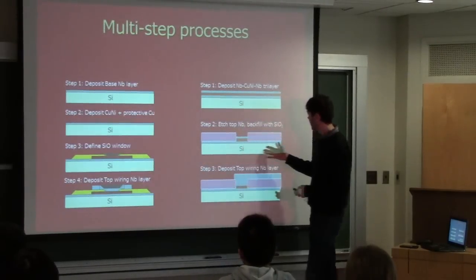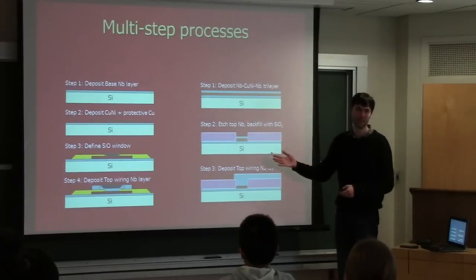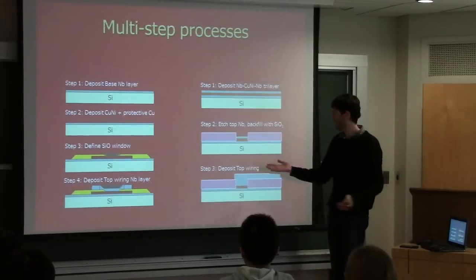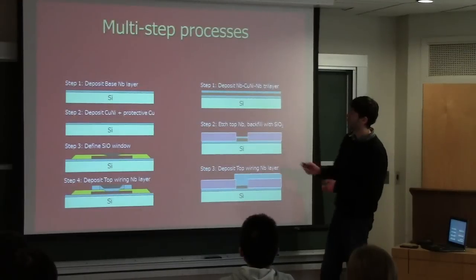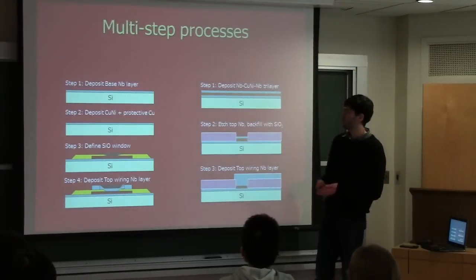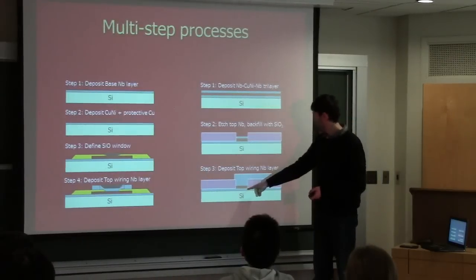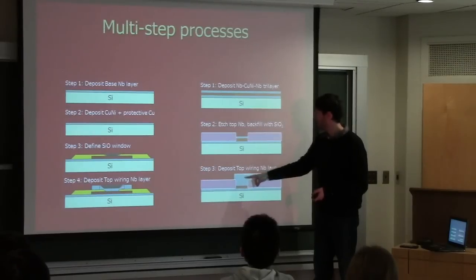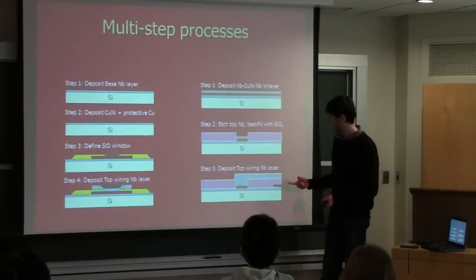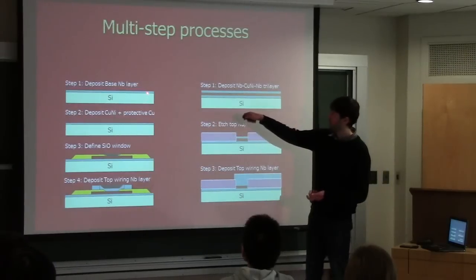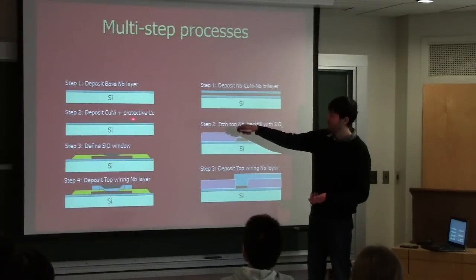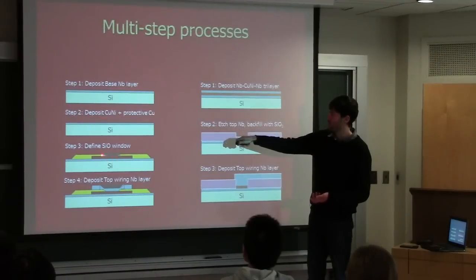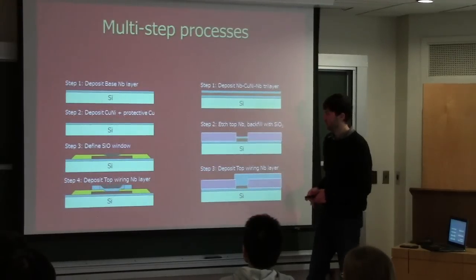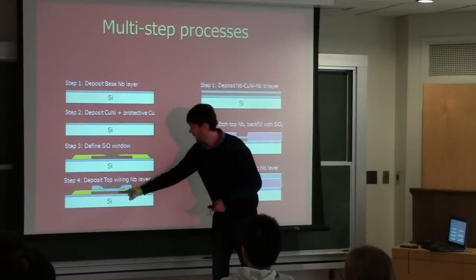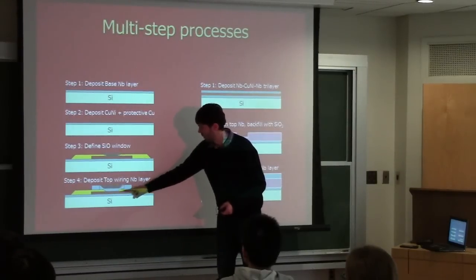For example, I took this from my thesis because I already had the slide and I was lazy to make a new slide. But here, starting from a silicon substrate, are a couple of different ways to make a niobium ferromagnet niobium junction. You can make a niobium layer which is flat, then deposit a patterned layer of ferromagnet, then make a window of dielectric, and then on top of that layer put another superconductor niobium, and then in this area you can observe transport from the top niobium to the bottom niobium.